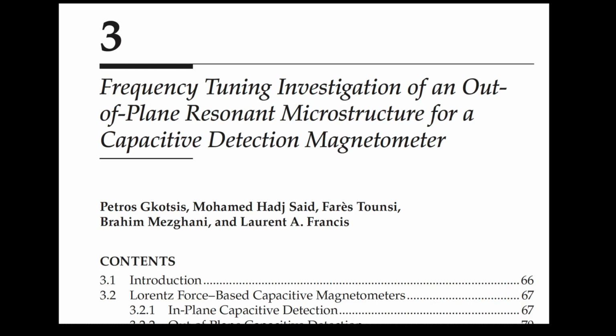Capacitive detection measures changes in capacitance between interdigitated finger electrodes on moving and fixed parts. The xylophone magnetometer design uses a clamped beam with hundreds of finger pairs fabricated using the SOI MUMPs process. The resonant frequency is around 18 kHz, and vibration amplitude increases with driving current, reaching a few micrometers at the beam center. Electrical characterization shows input resistance dominated by the gold layer, about 5.6 ohms below 100 kHz, and output